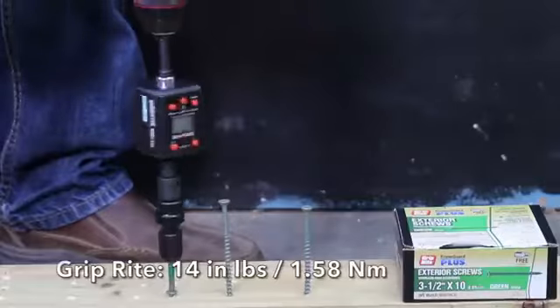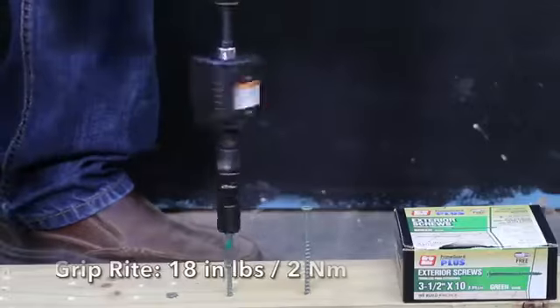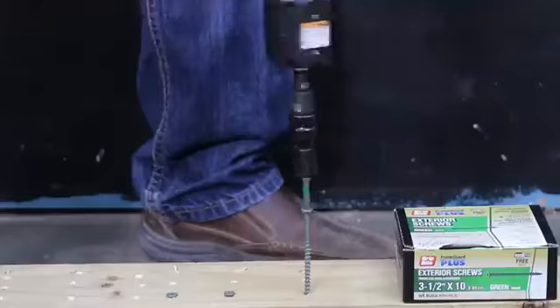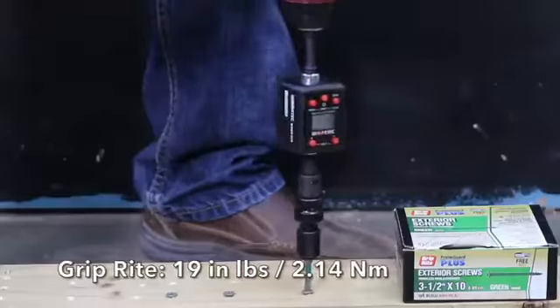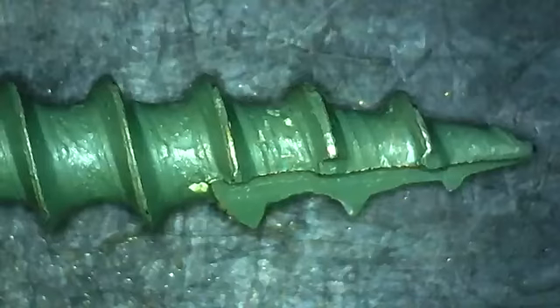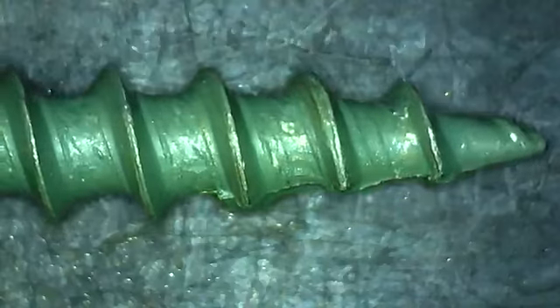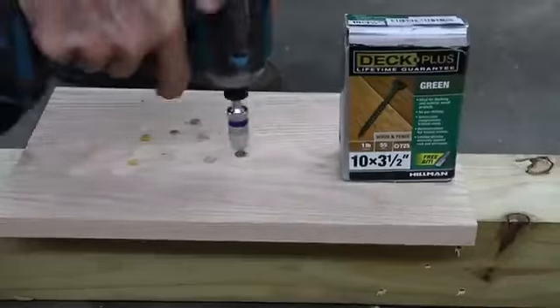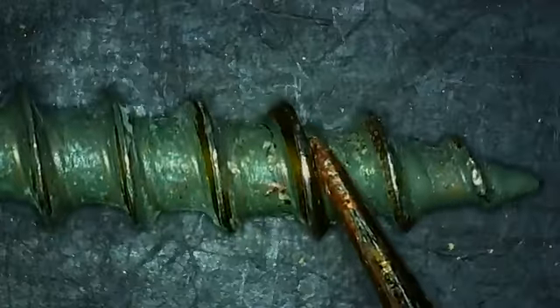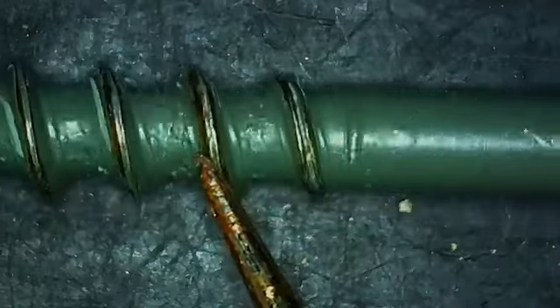14 inch-pounds to drive the first screw. And the second screw is quite a bit higher at 18 inch-pounds. 19 inch-pounds is the most yet of all the brands, with an average of 17 inch-pounds. And the coating on the Rite has held up the best yet and looks nearly as good as new. The Rite also held up really well after drilling through the oak. There is a small amount of metal exposure on the outer edges of the threads.